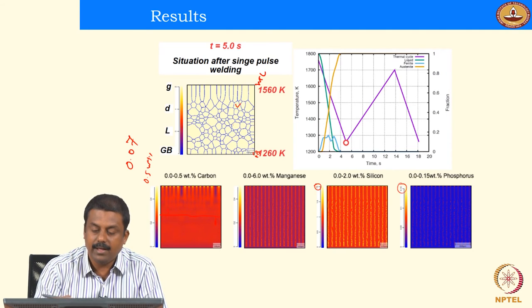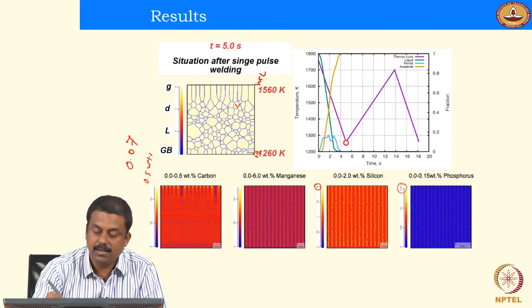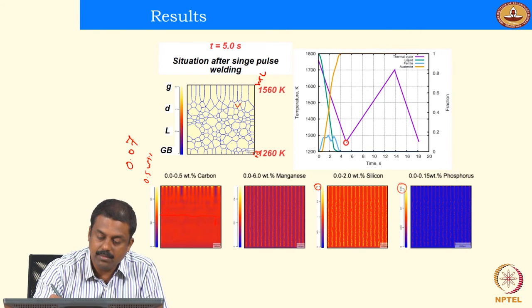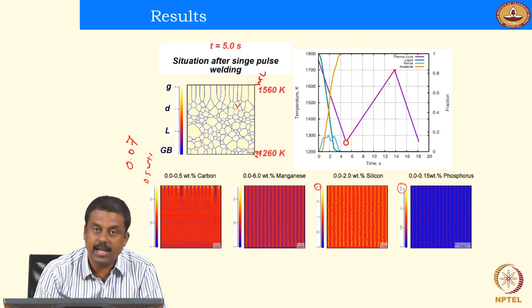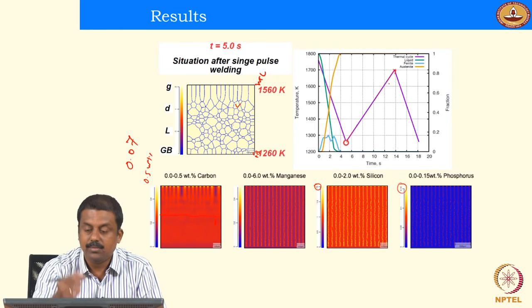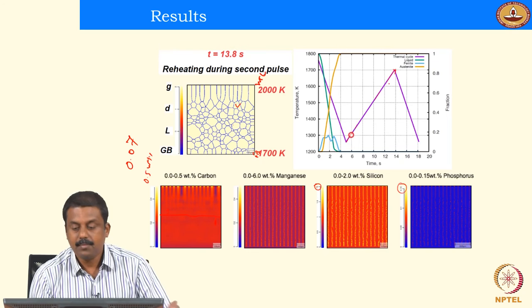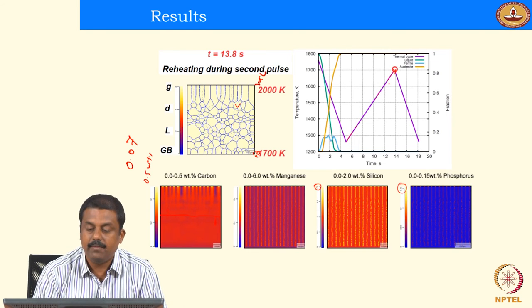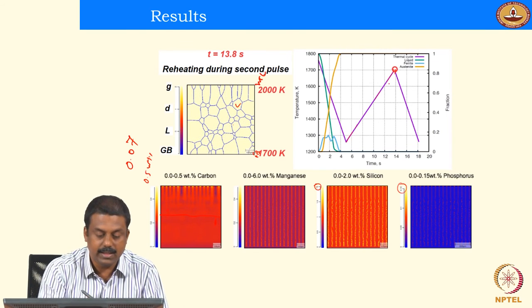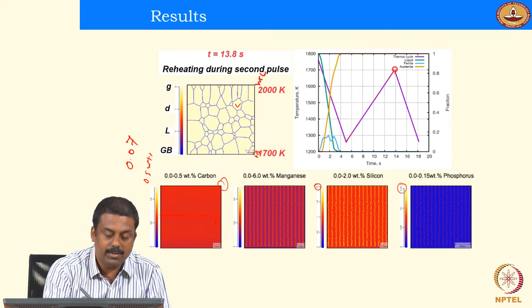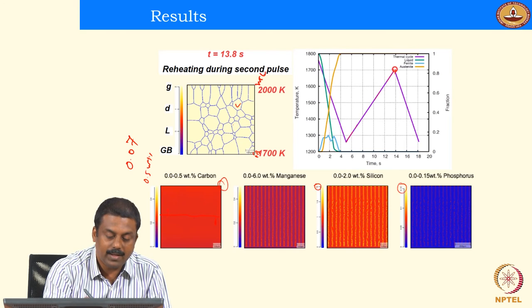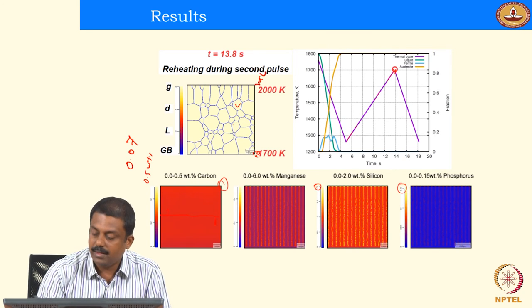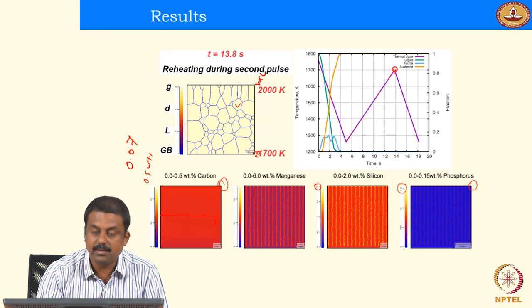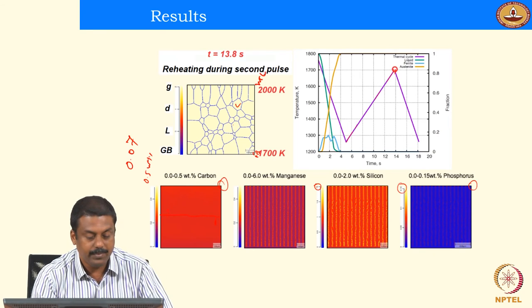So now, in our case, we have a secondary pulse, a second pulse, the double pulse is given, and during this process, instead of cooling to room temperature, what will we do? We are now taking again whatever solidified to another temperature. So again we are heating up to another temperature. You already see there is a homogenization. You see homogenization happened at the weld center line, and the carbon and phosphorus segregation is really reduced. You see that in the previous graph.